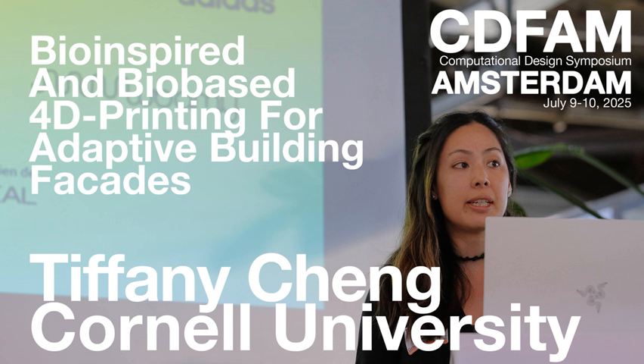geometry remained the same. So using the geometry, we can actually modulate and physically program areas with graded stretching, areas of high anisotropic stiffness, and also program bending in different directions. And so this biocomposite structure, just by acclimating to the moisture content in the environment, can transform from that flat state to a doubly curved geometry without any mechanical force, without any subtractive manufacturing, without any operating energy.